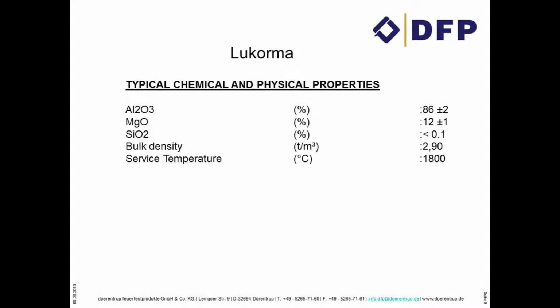The main ingredients of the neutral lining are Al2O3, the aluminum oxide, with MgO. It makes a spinel bond, and that is why the alumina refractory has a very high service temperature. It can withstand a temperature of 1800 degrees centigrade.